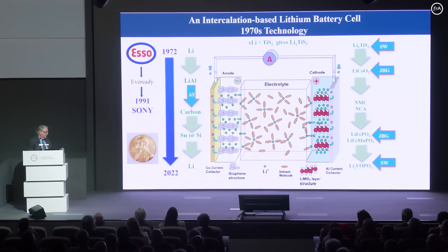So the lithium can insert itself in that graphite, but the challenge is you need over 70 grams of graphite to store 7 grams of lithium. So it's very inefficient, and the graphite also takes up half the volume of the cell. So if we want to make better batteries, we have to get rid of that. So right now the big effort is to move from carbon-based materials to eventually to pure lithium again, but in the meantime, tin or silicon, both those react with at least 4 lithium ions, so can store a lot of energy. But there are still some issues in making that successful.